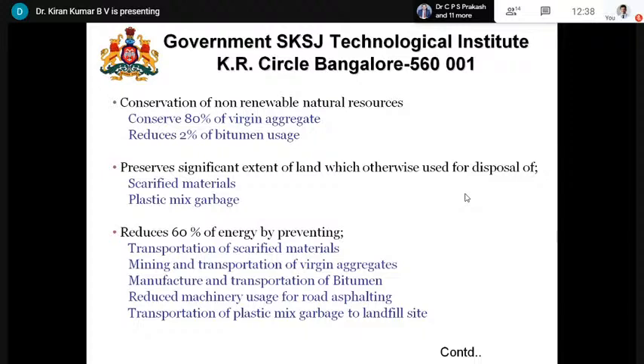In many cases in rural roads, low volume roads, which have about 1 MSA, million standard axles, they have used 100% virgin aggregate. We are talking about this new technology where we can save the virgin aggregate, using 20% virgin aggregate with the old 80%. It reduces the bitumen by 2%. This again comes with case to case aging characteristics of the material.